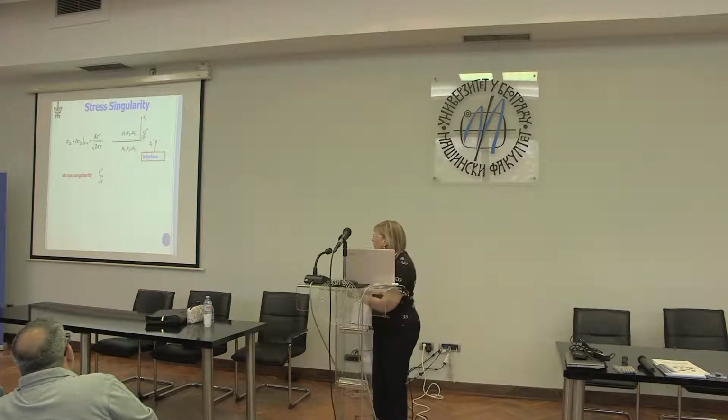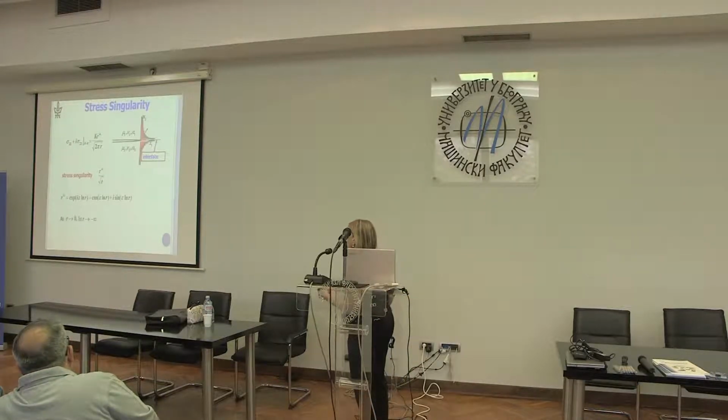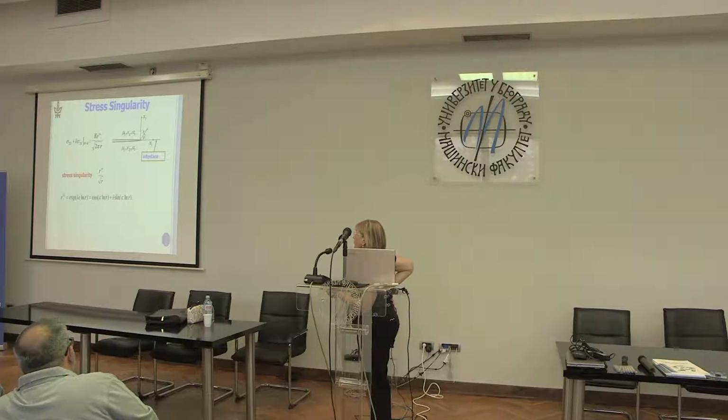So here's the stress singularity as I just mentioned. And let's look a little bit at the mathematics, how we deal with the stress singularity. If we take r to the i epsilon, we can write it as an exponential and a log. So we have e to the i epsilon log r, which works out to be cosine of epsilon log r plus i sine of epsilon log r. And if we took the absolute value of this, we would get 1. So the magnitude of this expression is just 1.